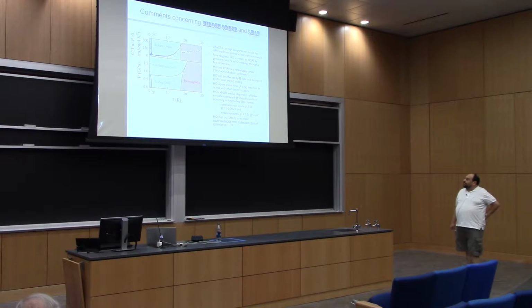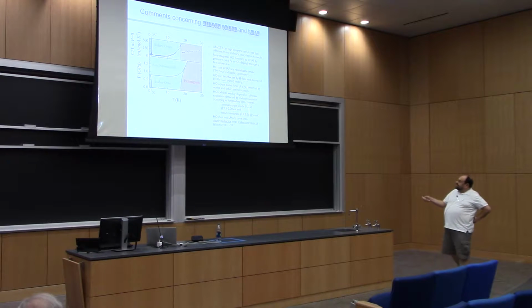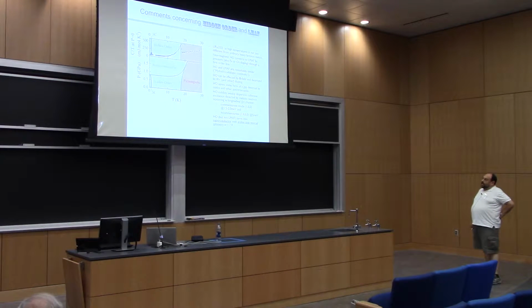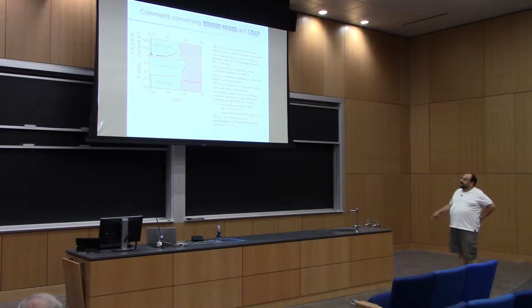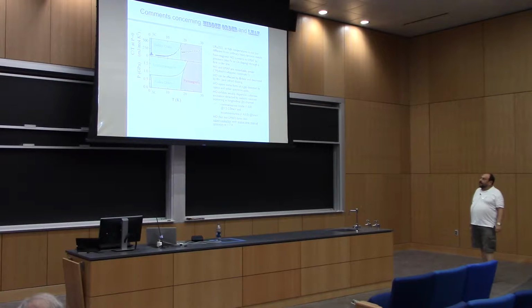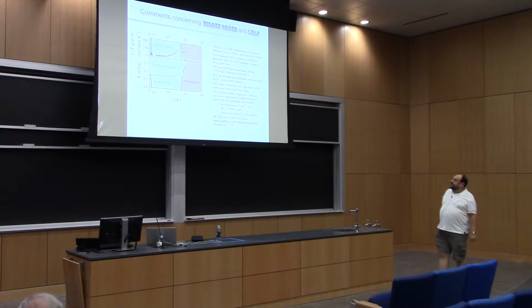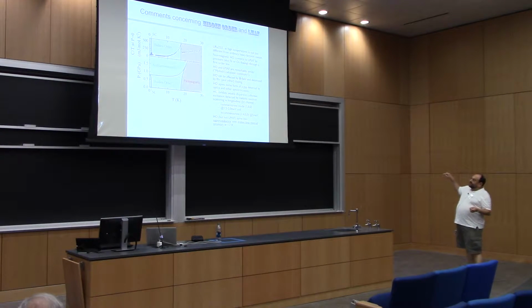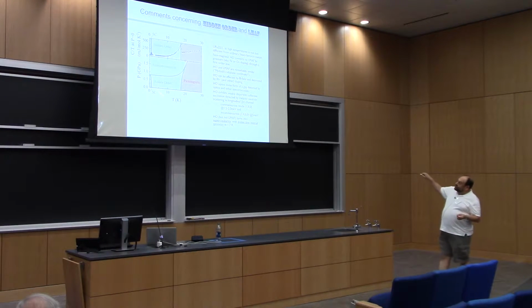I don't need to repeat what was said in the first two talks, but there is this list of very interesting properties, and I will mainly emphasize the connection between hidden order and the antiferromagnetic phase. Those are very similar brothers. This has a moment, this does not have a moment. It looks like the superconductivity appears only out of this hidden order state. So if that's true, then when the system is cooled from the paramagnetic state, this broken symmetry that happens in the hidden order state is required to get to the superconductivity, likely with broken time reversal symmetry.